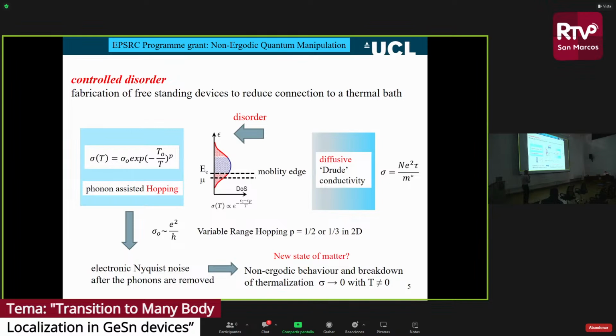What happens if you put disorder in? Here is a plot of the density of states as we go up in energy. Mu is the chemical potential, so that's where we're doped to in the band. So this band of carriers is doped to the chemical potential here. And when we have disorder, we have something called a mobility edge, so all states in the density of states above the mobility edge, this blue area here, they conduct. All states below this, they are localized and don't conduct, okay?